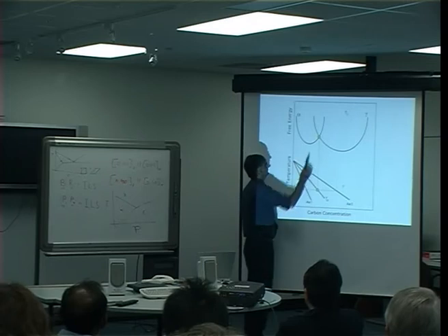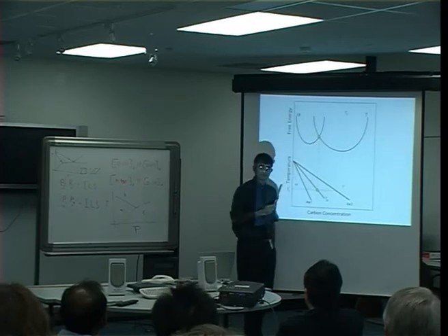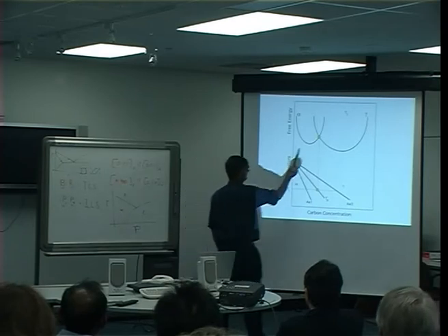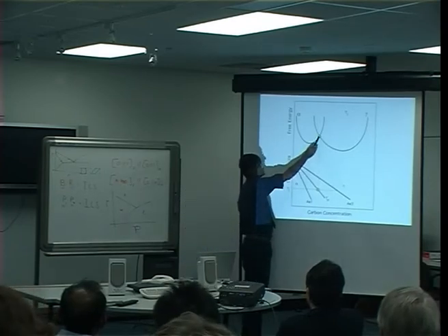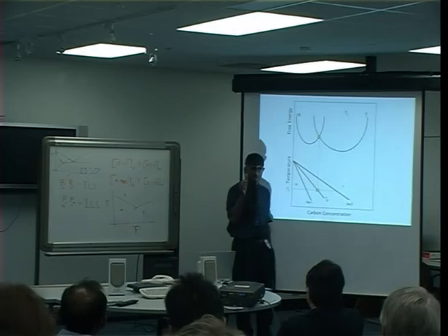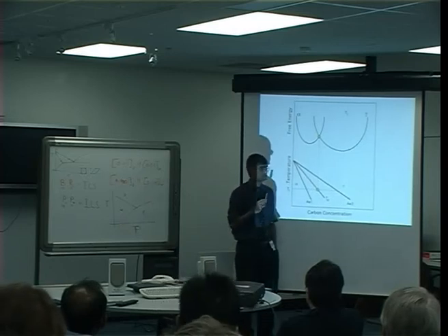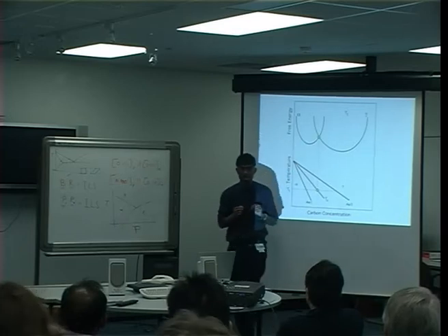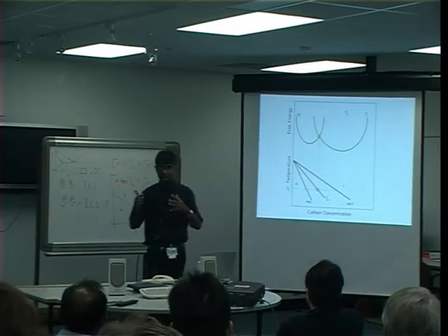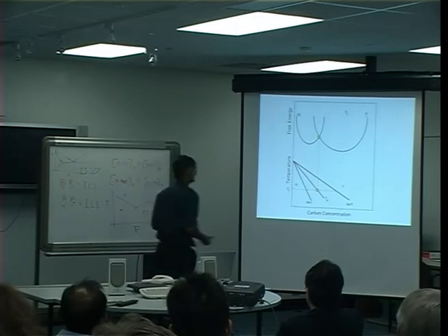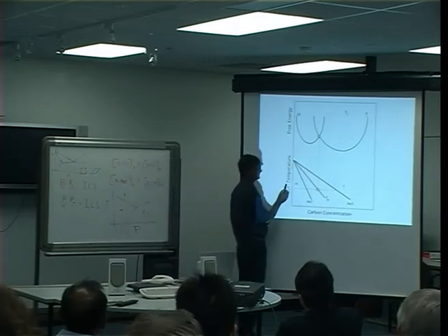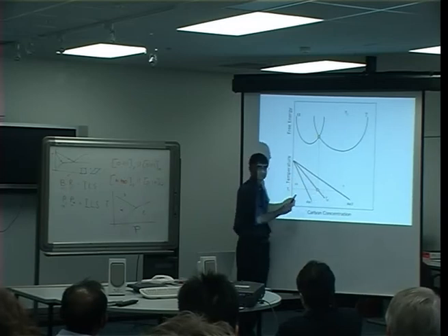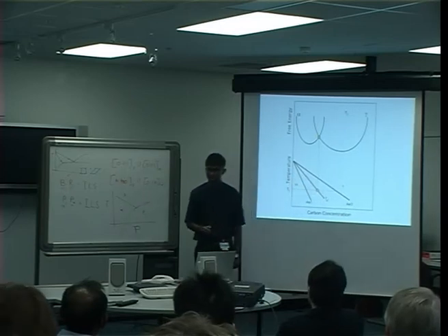Now, there is a point here which is not plotted on equilibrium phase diagrams, where the free energy of austenite and of ferrite is exactly the same for the same composition. So they have the same chemical composition and the same free energy. And we call that the T0 point. And if I extrapolate that point onto this diagram, where we are plotting temperature, then I get a curve which is not on the phase diagram. It's called the T0 curve.